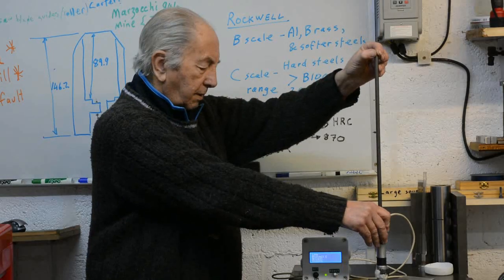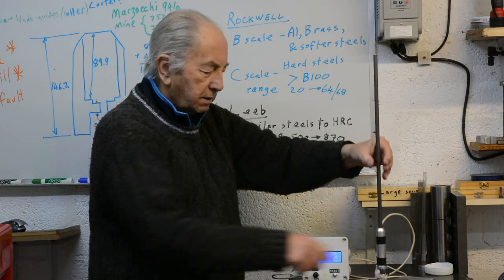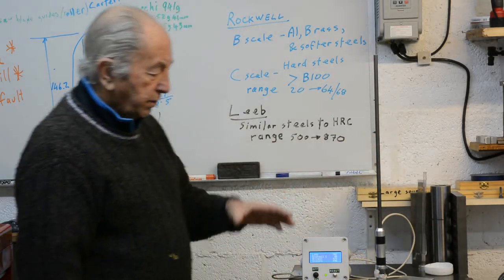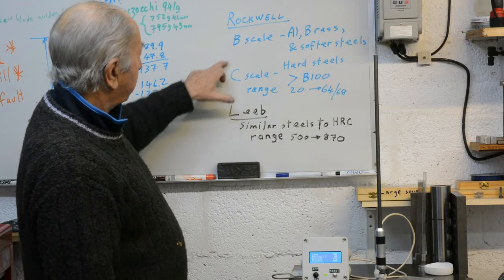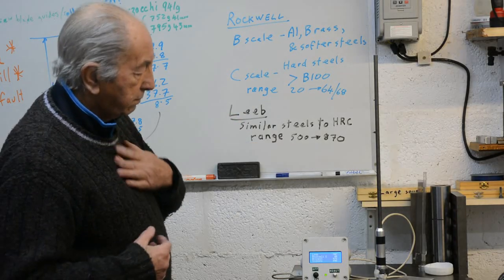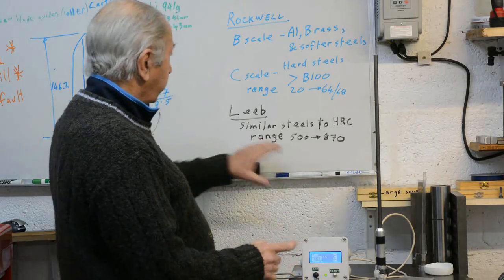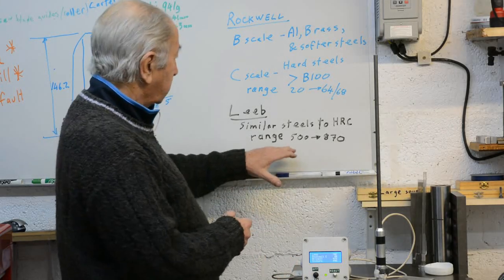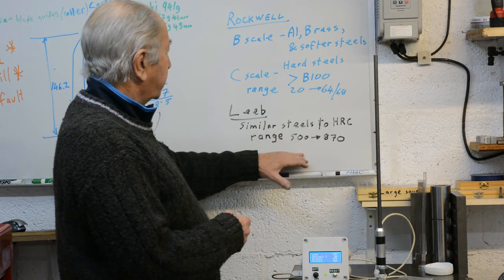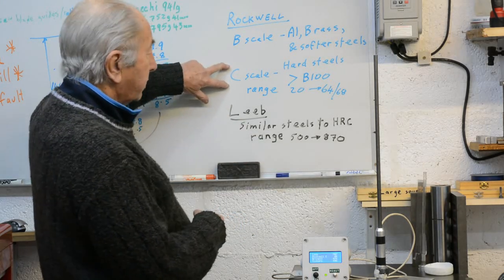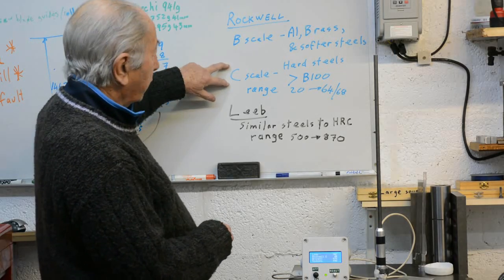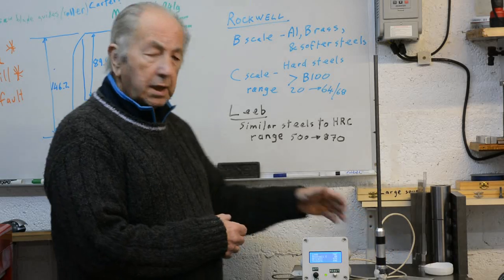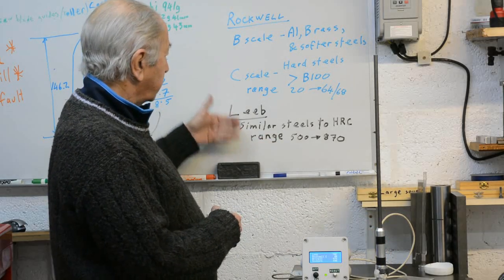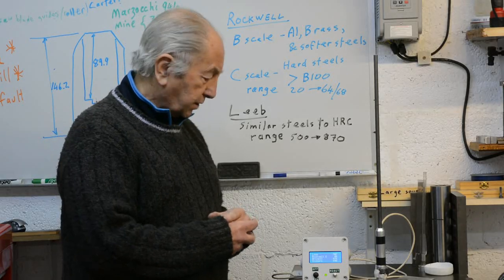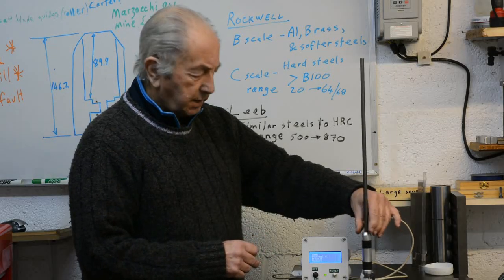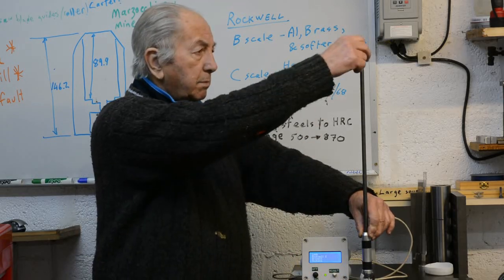For example, just done a test on some 4140 steel, which would be quite a legitimate steel to fit into the Rockwell C scale and the Leeb scales. And we've got a hardness on the Leeb scale, which is just the velocity ratio scale, of 707, and when converted to the Rockwell C scale, we've got a value of 48. Because this is a fairly hard steel, it would fit into the standards and the ranges of these two hardness standards. Now let's repeat that test on some 6061 aluminium.